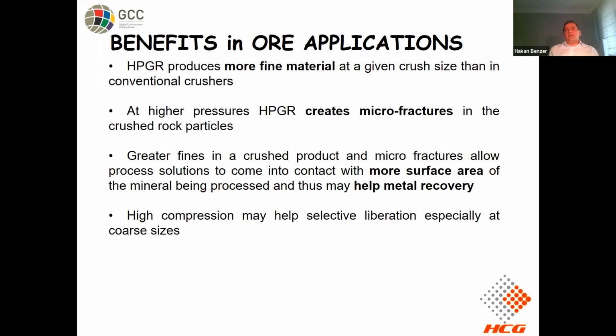What about the benefits, apart from the energy utilization, of high pressure grinding rolls in the system? High pressure grinding rolls, or vertical roller mills, or compressed bed breakage systems, first of all, produce more fine material compared to a typical crusher size. And all these data have been measured by ourselves. For instance, in the gold industry, we made that comparison and we observed a significant increase in the HPGR product. Roughly speaking, if you are effectively using your HPGR in a hard rock application, we can expect 40 to 45% of -1 millimeter material in the HPGR product. This is typical.